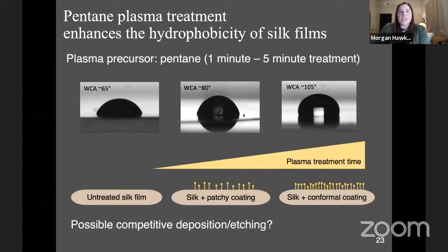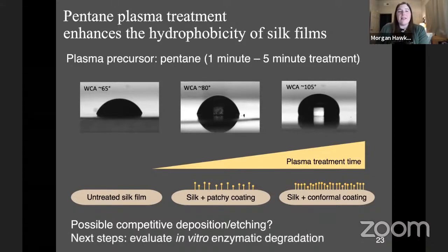Another interesting result that she's seen is that if the films are treated for too long, the contact angles that are measured are actually lower than that of the untreated film, which is very interesting and suggests that there may be competitive etching when the film is exposed to the plasma for increased duration. And we're currently characterizing the films using scanning electron microscopy to see if we can observe any changes in morphology that may arise from this prolonged exposure.